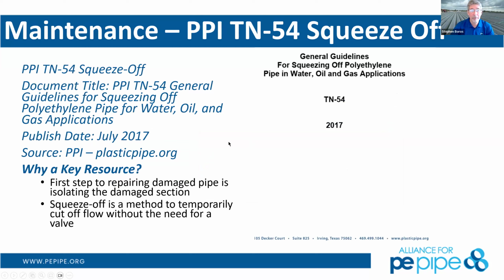Another thing that's unique to polyethylene pipe is squeeze-off. People that haven't seen this before don't believe it. But I can guarantee you it is true, it works, and it's a great aspect of polyethylene pipe that can be taken into account. It was actually pioneered by the gas distribution industry, to squeeze off polyethylene gas distribution piping to do a tie-in or repair and then open that pipe back up and the pipe's not damaged. You can do that with a pipe today up to about 24-inch diameter, which is about the largest I think they have a squeeze-off tool for.